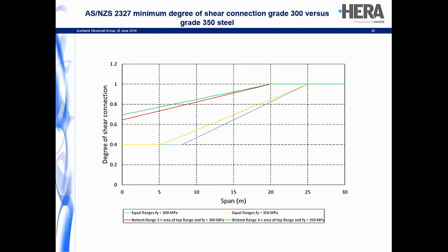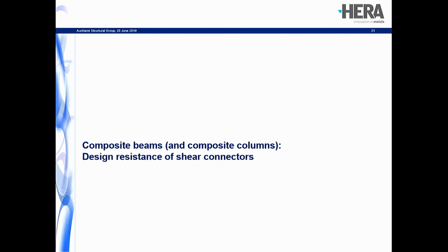The thing to take from this graph is that the degree of shear connection, and thereby the amount of shear connectors you have to provide on the beam, increases as the span increases. It increases as the steel grade increases, and it also increases if you have a large asymmetry in the cross-section. What I mean by asymmetry is the bottom flange of the steel I-section being a lot larger than the steel top flange. This is a graphical representation, but in the standard 2327 there's a set of equations that allow you to work out these minimum degrees of shear connection, and most pieces of design software already have this built in. So that's the importance of ductility in shear connectors.